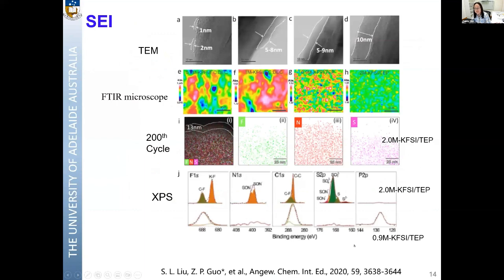Then to understand why this electrolyte performs so well in the cell, we did TEM and FTIR mapping. We can see after charge discharge, this SEI layer formed on the electrode. The thickness of SEI is around 10 nanometers. And from FTIR mapping, we can see the surface layer is very uniform, indicating the SEI is quite uniform. And after 200 cycles, the thickness of the SEI layer is around 13 nanometers, not a big change compared to the original state.